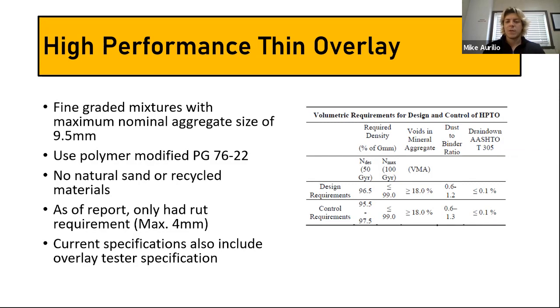So in this case, they were concerned. They understood that the design of the mix would be adequate for cracking resistance, but their concern was ensuring that it had adequate rutting resistance, because this is a mix that was designed with, I think it was either 6 or 7% AC content. So it's a very, very rich mix. They wanted to ensure that it wasn't going to rut, but they knew that because of the design, because of the extra polymer, that it would meet the cracking requirements.